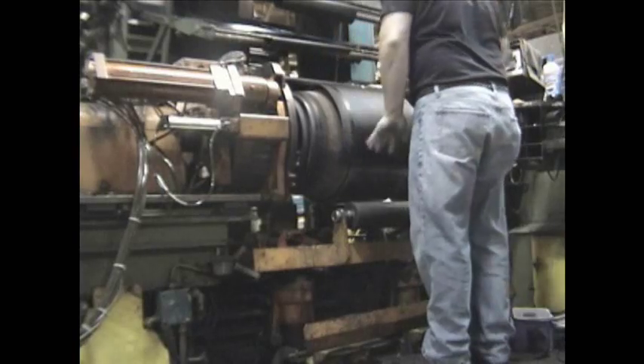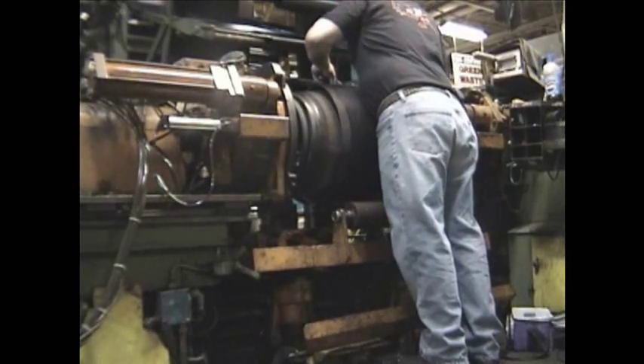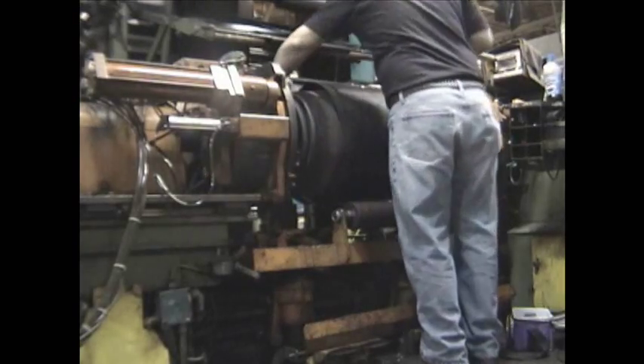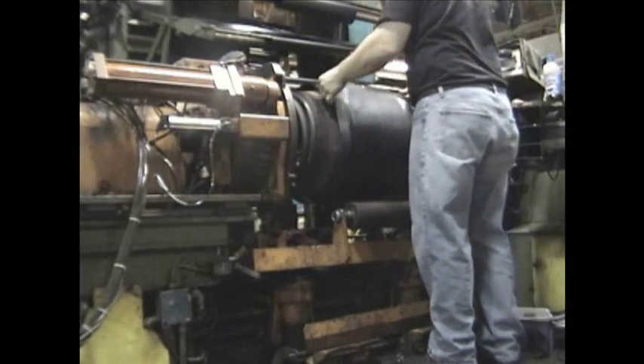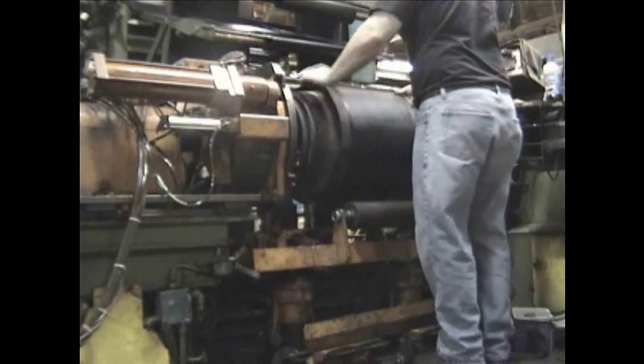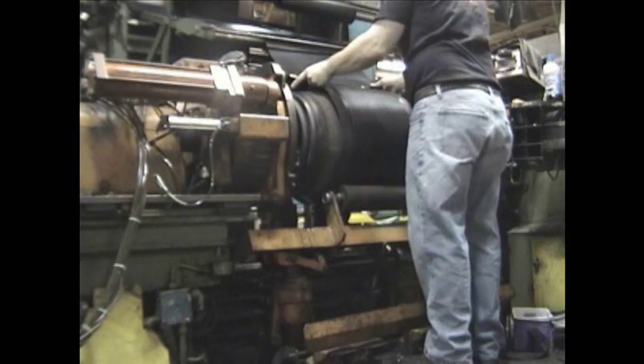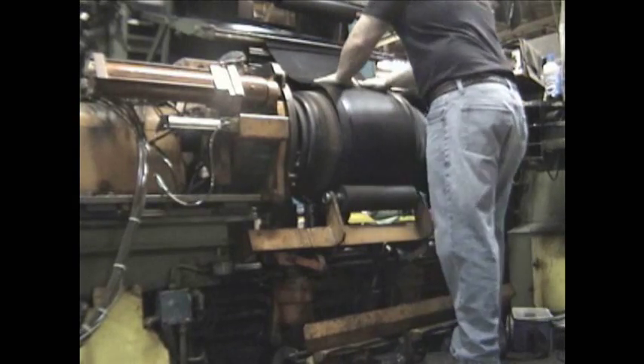The first part to go on is the inner liner. That sticks. It gets rolled around. Hand trim the inner liner with about a quarter inch overlap. Make sure it's lined up. Both halves have to be lined up. It has to be a good seam. Hit the foot pedal. You can see the bottom roller comes up to compress the plies as they go together.